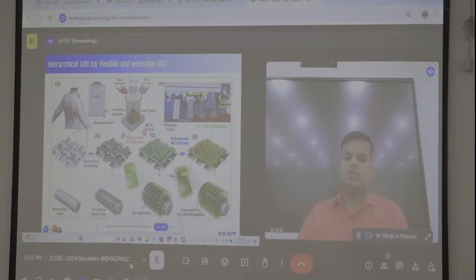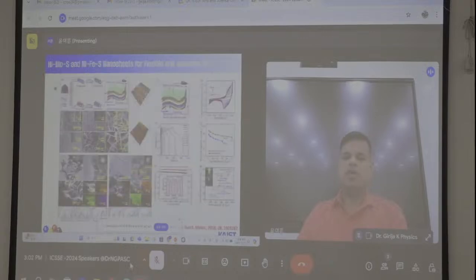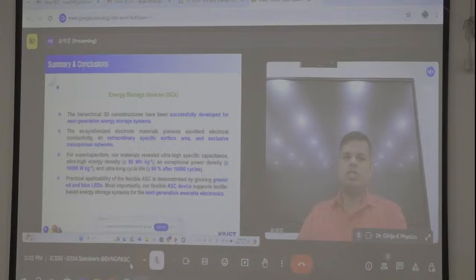And we also grow some material over the carbon cloth, because carbon cloth is not directly conductive, so we make the cloth conductive with nickel plating or copper plating. After that, we grow the material, and finally we use it. And this is also one of our studies, highly flexible energy storage devices.